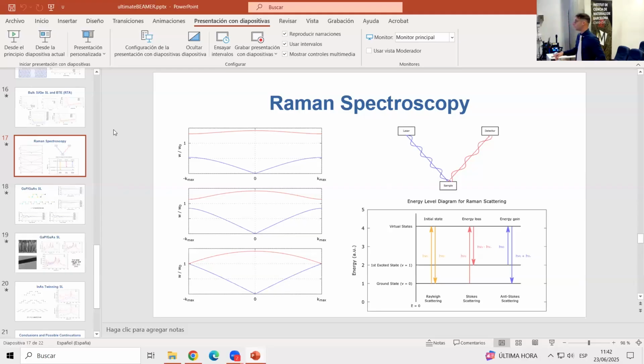Yeah, the reason is that you want to observe if your phonons could make a smooth transition to the zero-point energy, you could excite them in a continuous fashion, and you wouldn't observe any finite drop in the energy of the shift. You would just shine some light and see that some phonons start moving, but it's just like electrical conductivity. Imagine you apply a definite voltage difference to a conductor, and you will see a current which increases linearly with the applied voltage. In this case, you do not see any smooth excitation, and this is what allows the system to store some energy inside of it. An optical phonon can store some energy away from the zero point, and it cannot release it without an external excitation or absorbing.